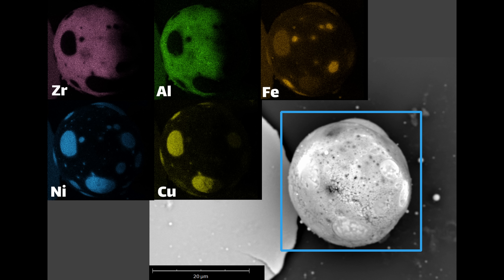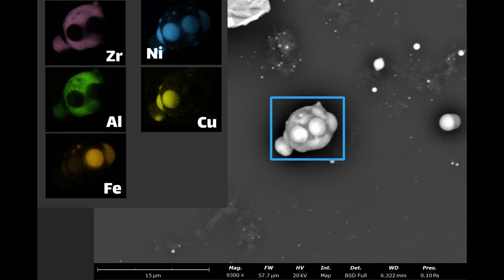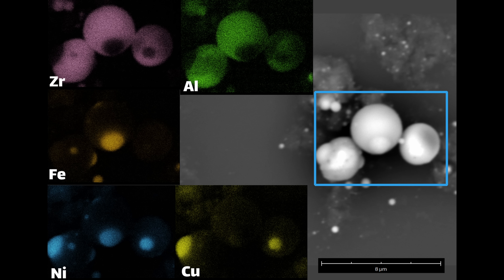The main bulk of the material tends to be zirconium and aluminum, with iron floating in between depending on the individual particle. What's happening here is when the material is ablated and in its molten state, there's enough material that as it hits the liquid it's not immediately quenched — there's a little bit of time for the different elements to segregate and separate into different phases. You tend to see nickel and copper move to the edges while aluminum and zirconium stay in the middle. This is a failure case — it's not a high entropy alloy, it's really just multiple alloys glommed onto each other.